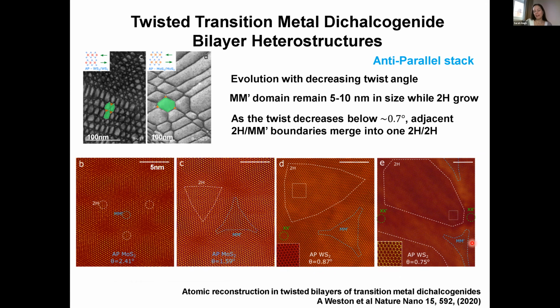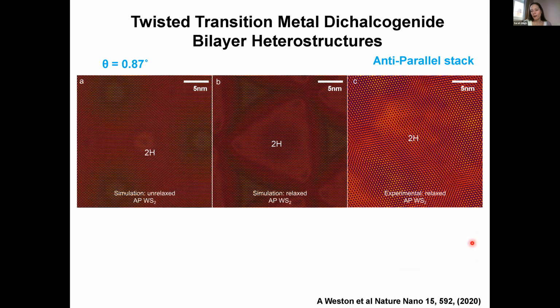And even if we make the angle much, much smaller, these domains seem to have a fixed size of about 5 or so nanometers. Whereas as we get that angle smaller, those 2H domains are able to get larger and larger. So you can see here, this is the unreconstructed simulation on the right, this is the reconstructed simulation, and this is the experiment. It's a bit difficult to see that comparison because of the large scale of the data. These domains are of the order of tens of nanometers or larger.